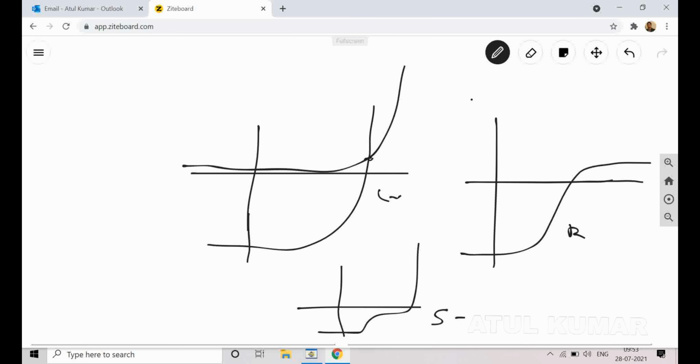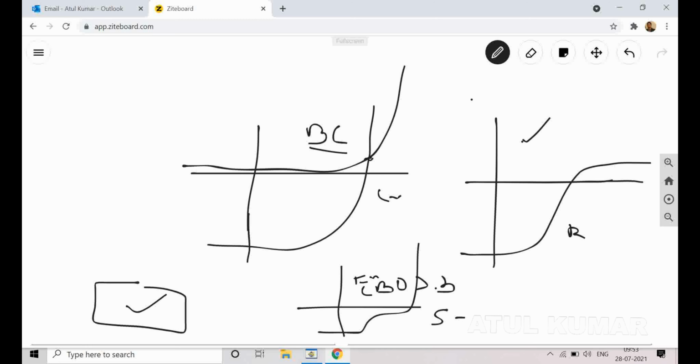So these three IV curves signify that some particular dominant recombination is going on in the device. This one signifies the presence of a back contact barrier. This one signifies that along with the back contact barrier you have a high defect density also. And this one signifies interface defects along with conduction band offset, CBO, greater than 0.3, which I took, and only then it was visible, and interface defects are also high. So those things it is signifying.